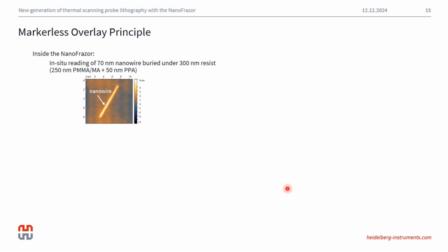Now, if we're talking about nanowires or flakes and adding contacts onto those, this is particularly difficult when it comes to standard lithography techniques like photolithography or e-beam lithography, which use alignment markers for this purpose, because these materials can be randomly distributed on the substrate. However, with the NanoFrazor, we can overlay new patterns onto existing ones on the sample without any markers at all.